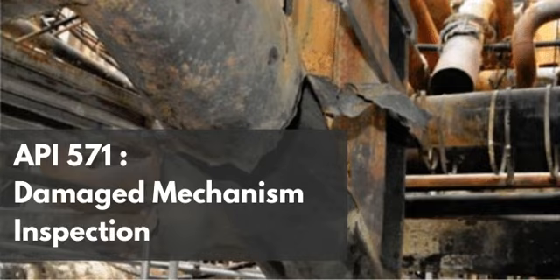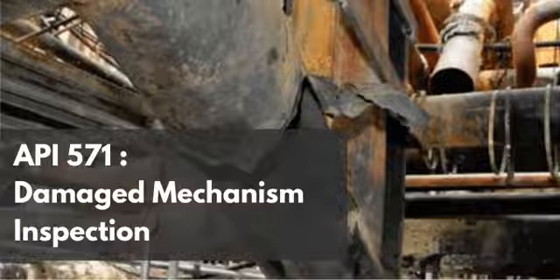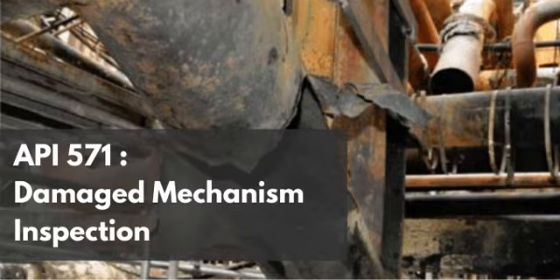Now, before we conclude, we must address the final operational warning in the text. This is a trap that catches even experienced maintenance planners. Oh, the pre-work trap. Yes. It involves the preparation of the equipment before the welder even arrives to make a repair or apply a heating band. The text emphasizes the strict requirement to thoroughly water wash non-PWHT'd carbon steel piping and equipment prior to welding, prior to heat treatment, or prior to steaming out. This is a highly critical safety and integrity directive.